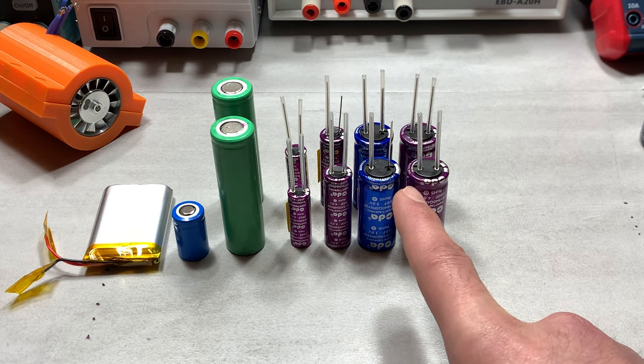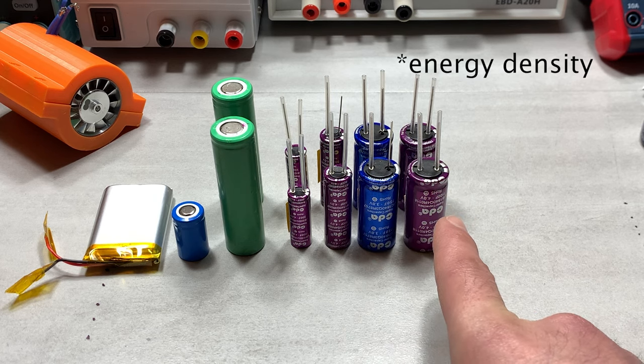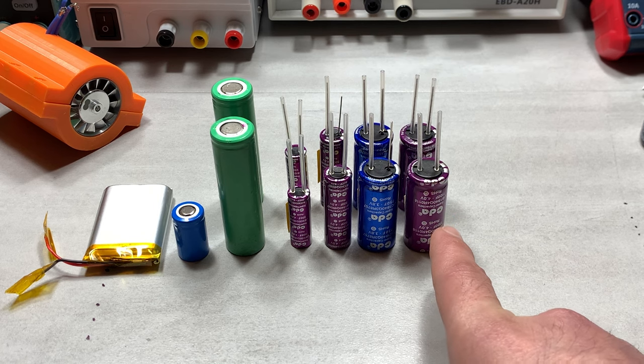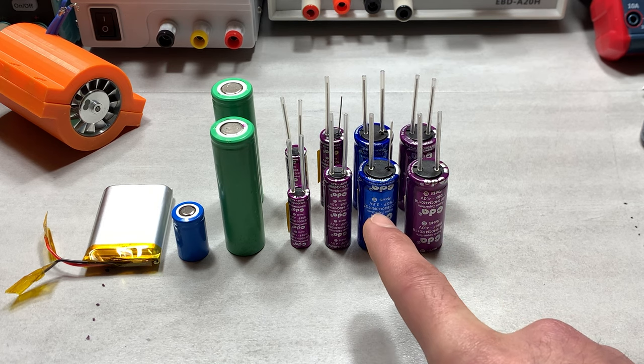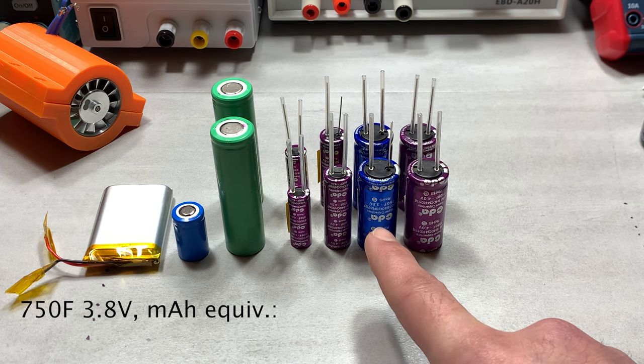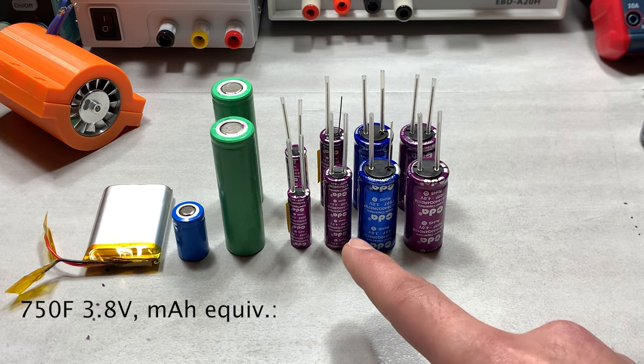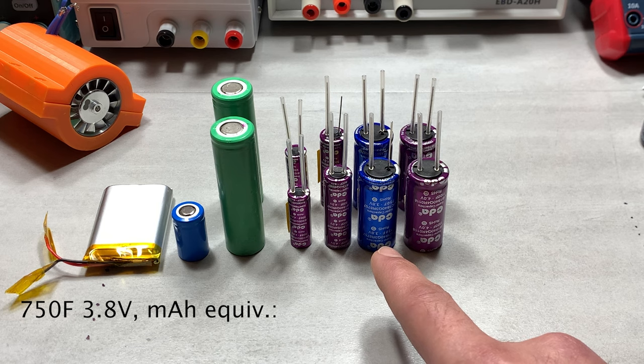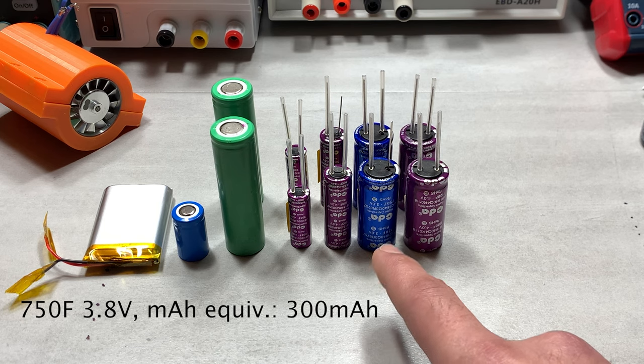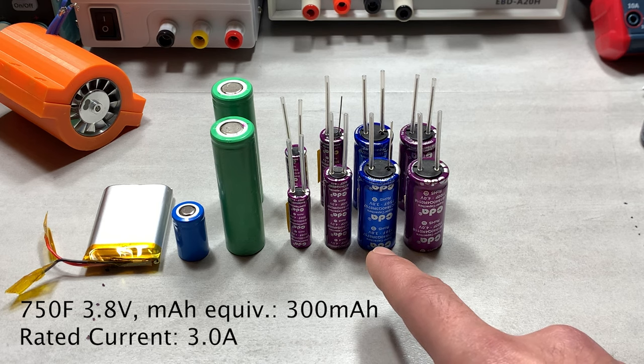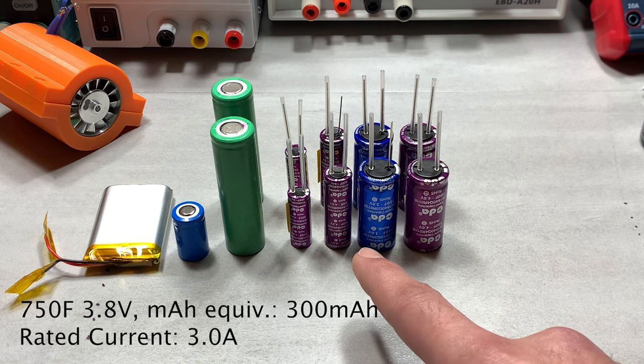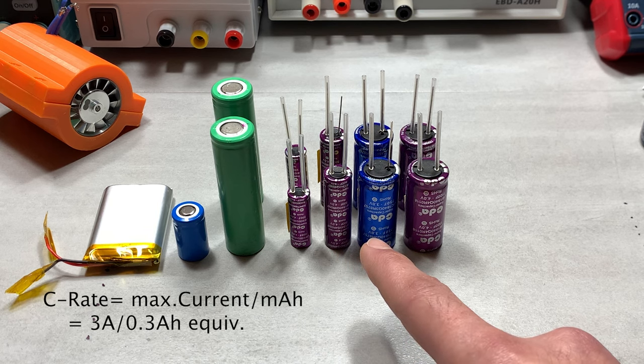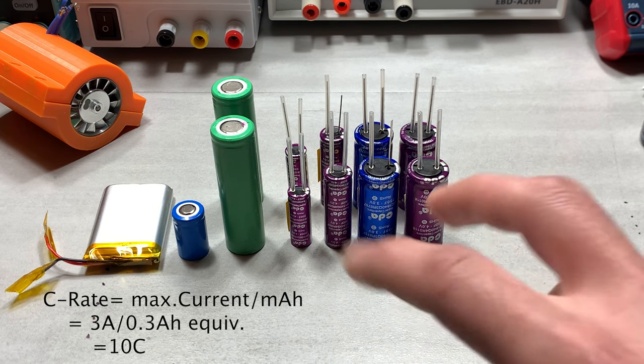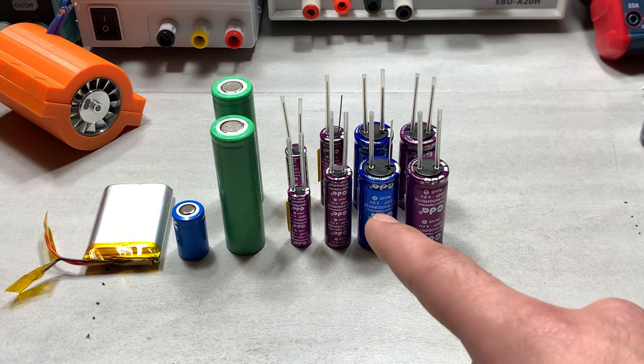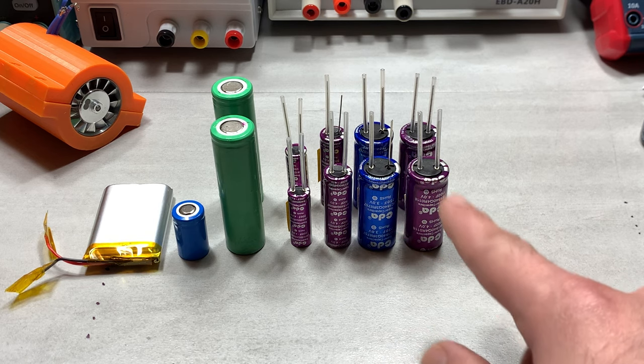So they do have a lower current density than the 1100 farad ones, where we actually cross over into kiloFarad territory. But with the 750 farad 3.8 volt cells, they have a milliamp hour equivalent rating of 300 milliamp hours, with a much lower rated current for operating of 3 amps. So dividing 3 amps by 0.3 amp-hours gives us only about 10 C. And I know I say only about, that is pretty good, but there's going to be a massive difference once we step up to this one.